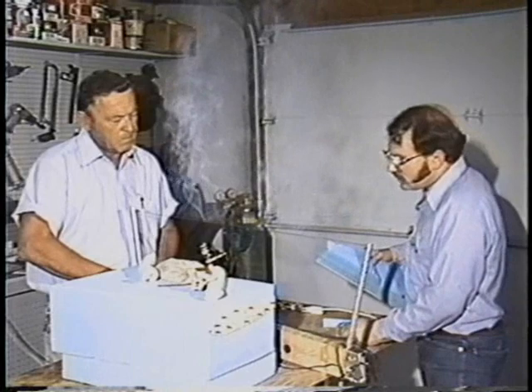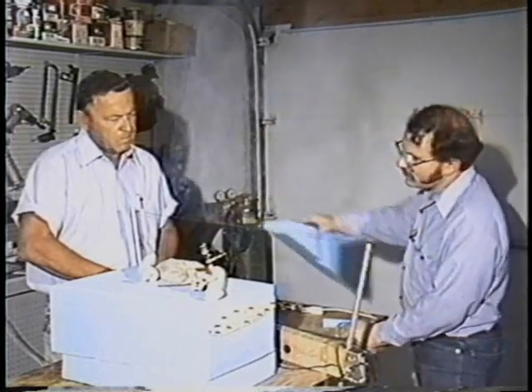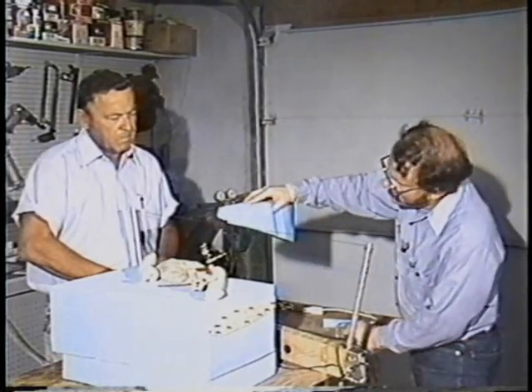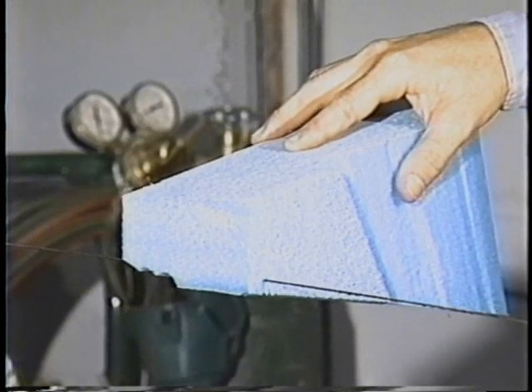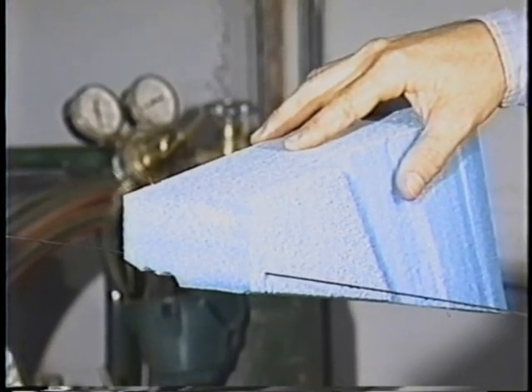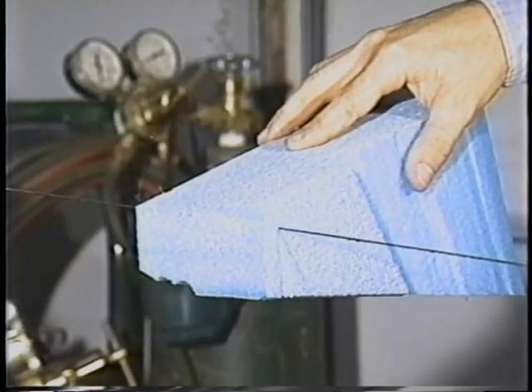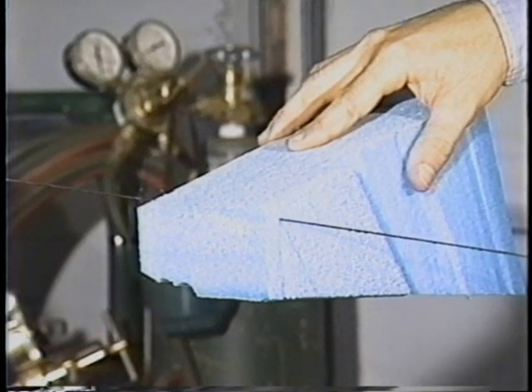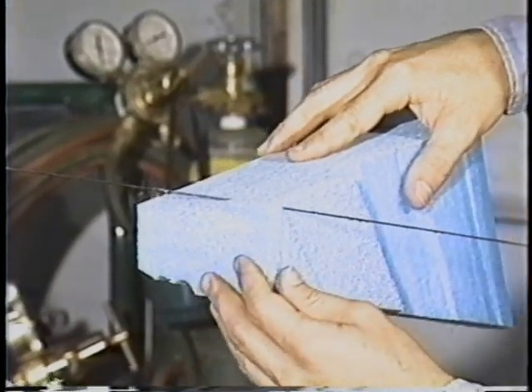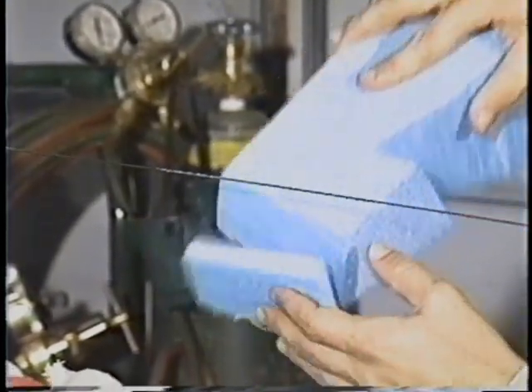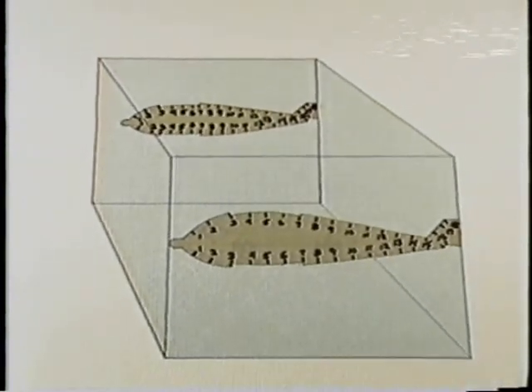Too hot. A wire that is too hot causes burnback, the melting of the foam along the cut. A wire that is too cold causes wire lag, distorting the airfoil. When the temperature is just right, the wire will slice through the foam almost effortlessly. And the proof that it's correct will be the strands of fibers the wire pulls from the foam when you've completed the cut. To illustrate the hot wire technique for cutting airfoils, let's pretend the foam block is transparent.